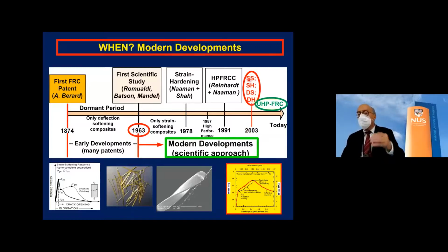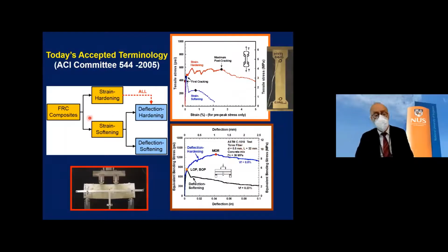And in fact, as a result, we had deflection softening and deflection hardening. So it follows from tension softening to deflection and so on. And the sketch for it is shown here. All FRC composites are strain hardening or strain softening. Some of the strain softening can give you deflection hardening. All the strain hardening give you deflection hardening, and so on. Otherwise you get deflection softening. This is a visual of tension and compression.